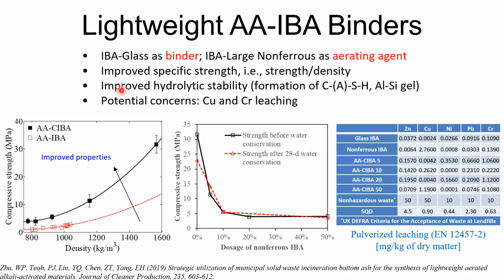By understanding that, we try to consider if we are able to mix IBA glass to form a binder, and then use the large non-ferrous particles as an aerating agent to produce what we call high strength and low density AA-IBA binders.